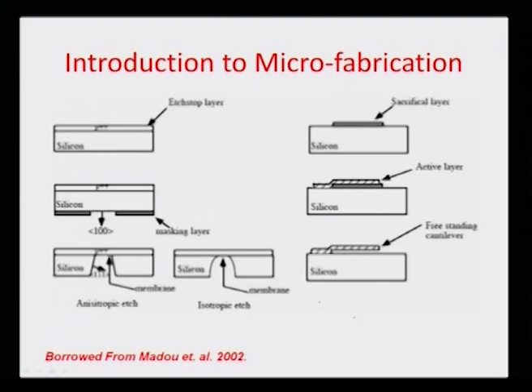For example, here is a slide which has been borrowed from Dr. Mark Madou's book on microfabrication. So here it is showing how you can formulate a P++ membrane, and this has already been illustrated. So you can actually formulate a small cavity here using resist, and this can be used as an etch window, and there can be an etchant which is selective to P++, which is actually highly doped positive silicon on the other side. And so the material starts etching away in an anisotropic manner, thus formulating a 54 degree angle. And based on this, it just goes up to the selective layer here, which is the P++ layer, and stops the etching process, thus creating a membrane.